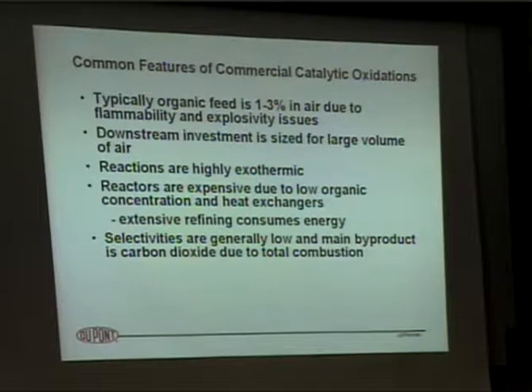They're incredibly exothermic, so you get a lot of heat exchange investment to take the heat from the reaction, prevent the reactors from running away. Extensive refining, which is another global warming issue because it takes energy to refine and boil up and distill all of this inert material that goes through the process. And the selectivities are generally low. So you've got to distill and take this small amount of product and purify it. So if you're feeding, for example, 1%, take for example butane to maleic anhydride. If you have a 50% selectivity, you've got a 0.5% maleic anhydride that you take out of a stream containing 99.5% other stuff. So it takes a lot of refining and uses a lot of energy to do that.